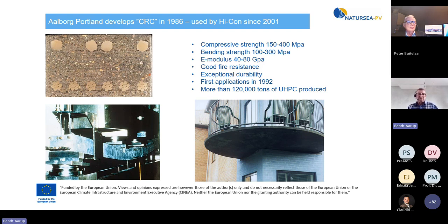very high strength matrix with steel fibers, and in our case we also use conventional reinforcement together with this type of matrix. So compressive strength 150 to 400 megapascal, depending on whether we use heat curing or special aggregates. In our production, average strength is about 170 megapascal for the things that we produce. Bending strength depends on the rebars.